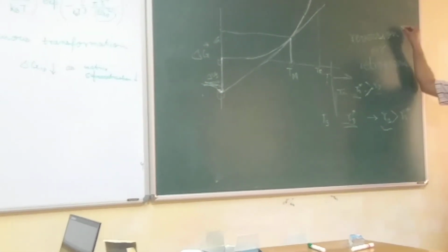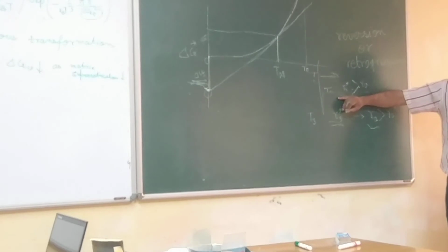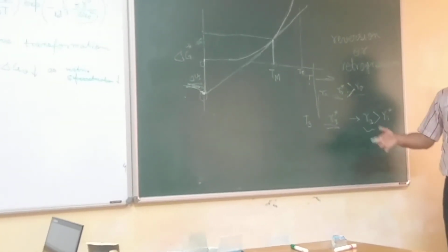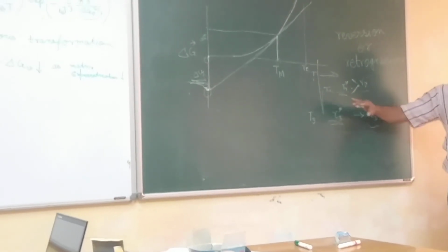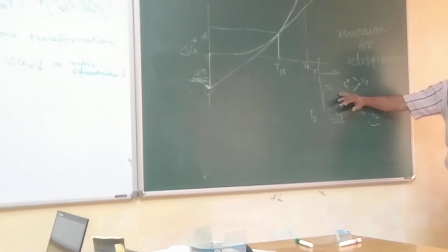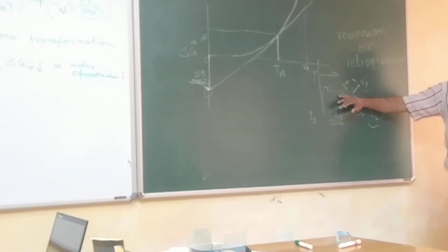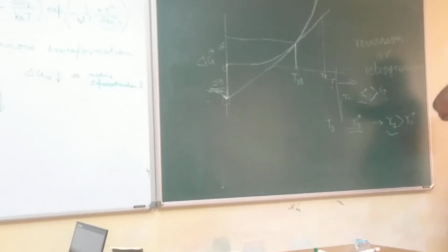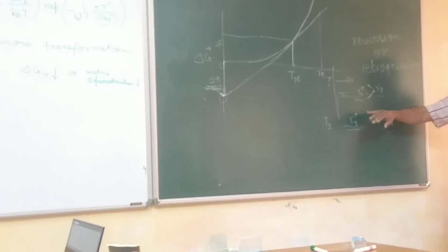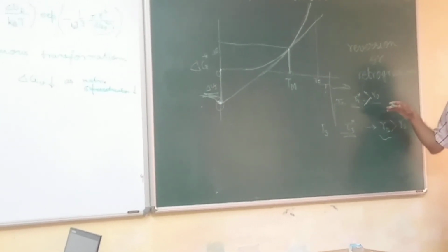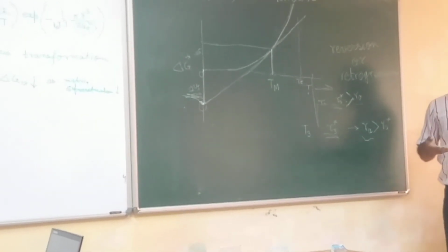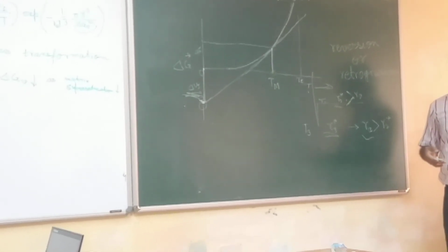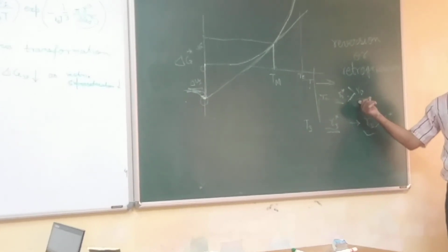So this going back to the solution, even though that is thermodynamically stable, will take some incubation time to get to another size distribution of the embryos, that is NR. At different size, what is the number of such embryos? So NR corresponding to this temperature will form, and then the steady state nucleation rate will start. So that incubation time is required.